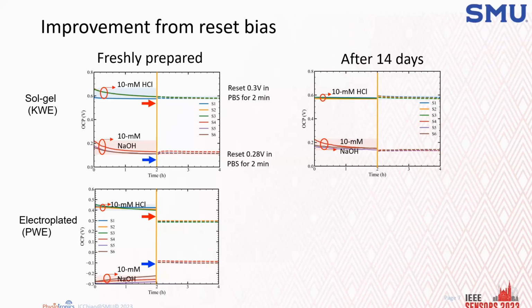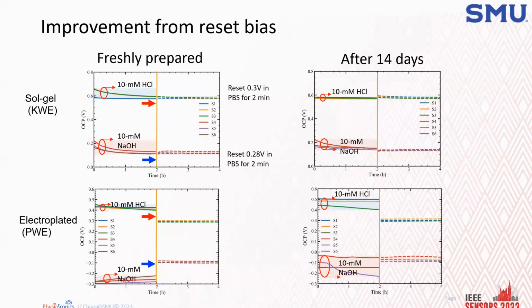For the sol-gel one, you can see that in the beginning, even we didn't reset the voltage, the potential was very similar to previous, except the alkaline has a little bit drift problem. But after 2 hours, we reset them again, then the potential becomes flat again. For electroplated, after 14 days, however, the drift become the same or worse. We believe that this is the hydrous water molecule doing its work. However, even it has drift, after 2 hours, we reset the voltage and it becomes flat again.